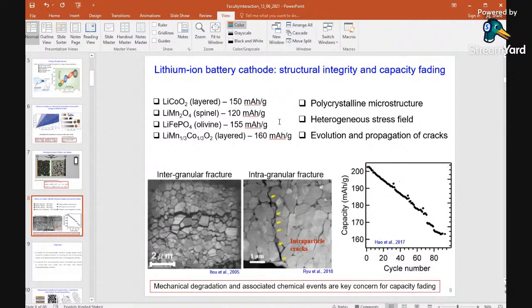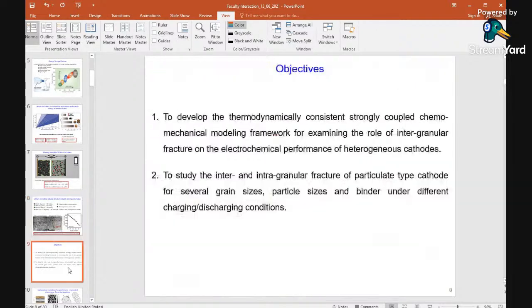So what is the problem? All these cathodes have a polycrystalline microstructure, and they create a heterogeneous stress field when the lithium is intercalating or de-intercalating. This generates the evolution of cracks, or different types of cracks. And what will happen once the crack is generated? There is no path for the lithium ion to go from one side to another, and for the electron also. So the mechanical degradation and associated chemical events are one of the key concerns for capacity fading. The objective of this presentation, the work we have done, is to develop a thermodynamically consistent, coupled chemomechanical model for this fracture, and later we extend this model to intergranular fracture for the particulate type cathode.